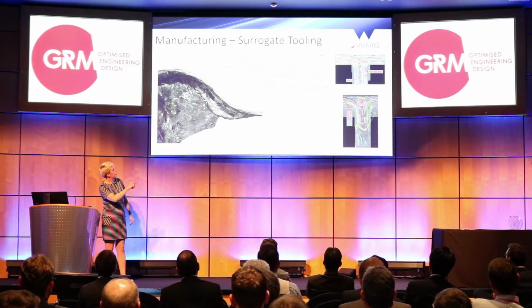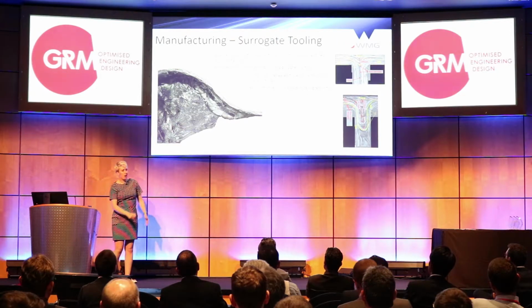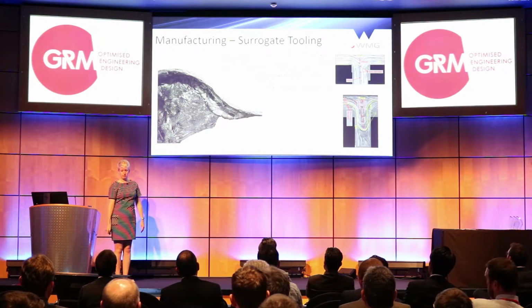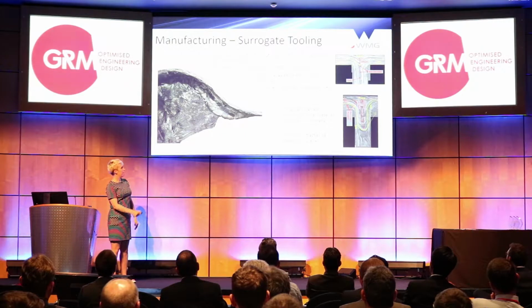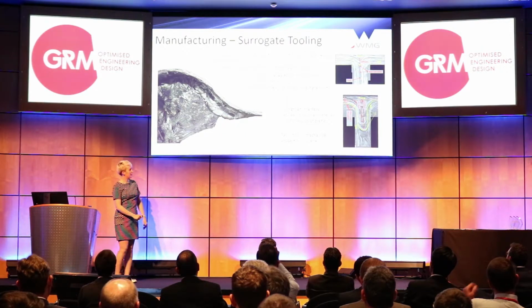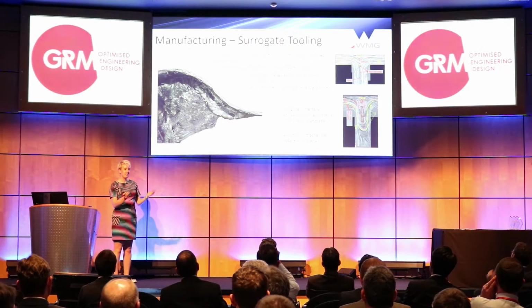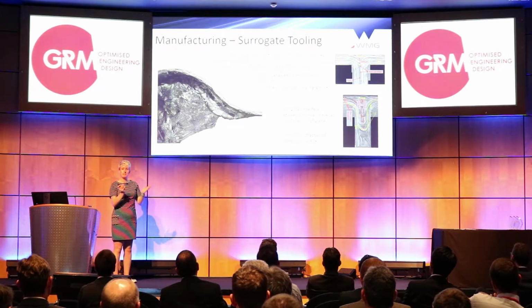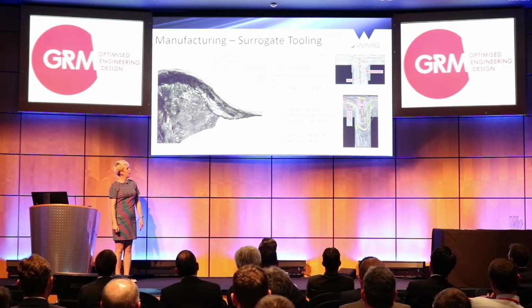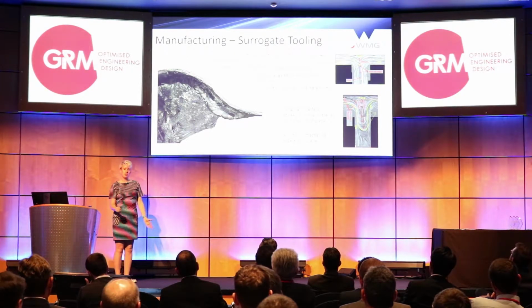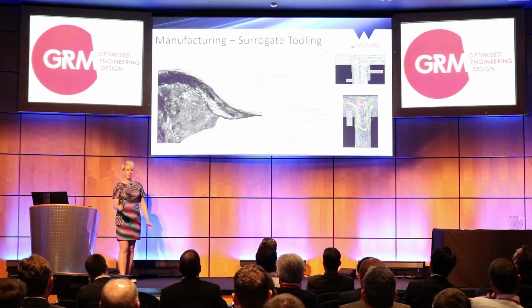This one was done by burn off, so we just burnt off most of the resin to keep the structure intact and have a look. So, forever the optimist, the pro of this prepreg moving is that we can strengthen this interface by pulling some fibres into the Z direction almost, where generally you wouldn't have any fibres in the right orientation. The con, of course, is that you get a reduction in the mechanical properties where you'd originally placed them.